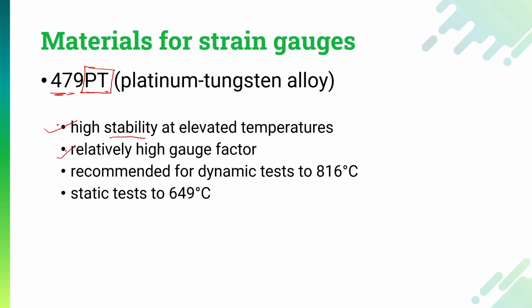A gauge of this material is recommended for dynamic tests up to 816 degrees Celsius and static tests up to 649 degrees Celsius.